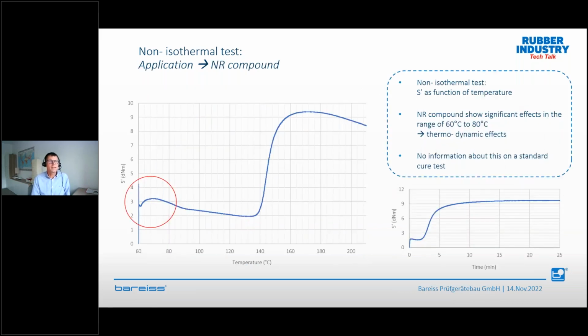first, a nice example on a natural rubber compound. On the right side, you see an isothermal curve where you see nothing really special. But when you look at a lower temperature, around 60 to 80 degrees, the torque is increasing, but the temperature is also increasing. So normally we would expect the torque to decrease. This happened, and this is a temperature which occurs in your mixer, for example, when you put the natural rubber polymer in the mixer.